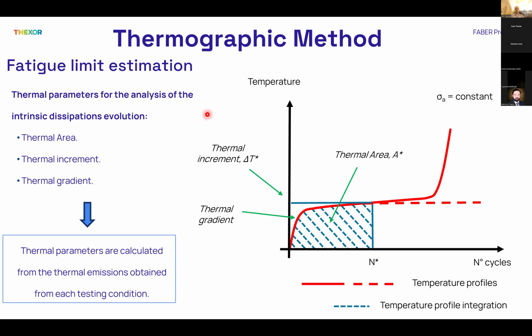The first possibility is the thermal area, which consists of the area subtended to the thermal profile. The second possibility is the thermal increment, which consists of a temperature increment of the thermal profile. The last possibility is the thermal gradient, which takes into account the transient zone.